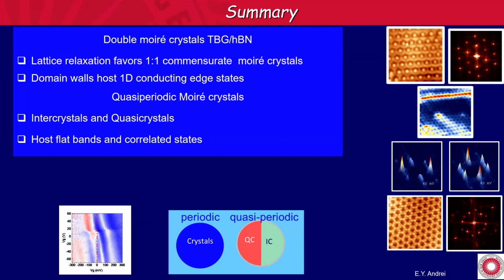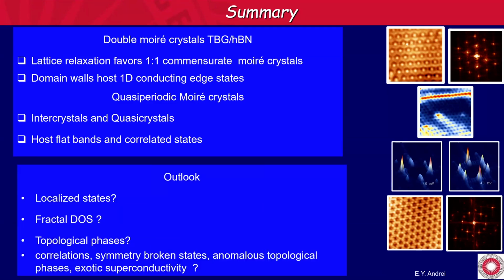So this brings me to the summary. The take-home message is that lattice relaxation favors one-to-one commensurate moire crystals. Domain walls host 1D conducting edge states. And when you have quasi-periodic moire crystals, you have two kinds, the intercrystal and quasi-crystals. I don't think there's a fundamental difference between them. It's just to placate Paul Steinhardt. I actually don't know if there is a real difference. They host flat bands, correlated states, and the jury's still out, and there's lots and lots of things that remain to be done. And thank you for your attention.